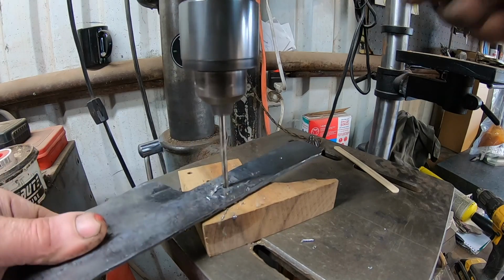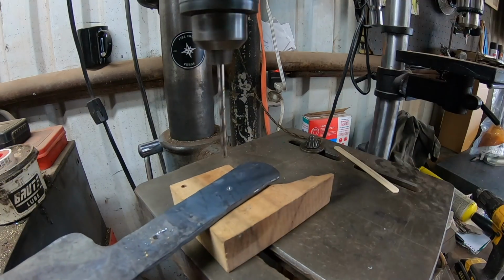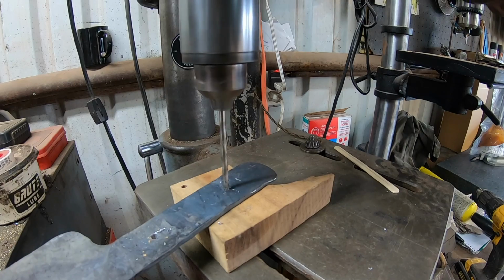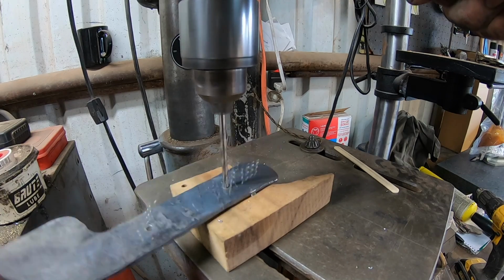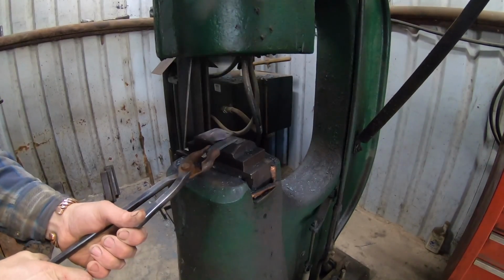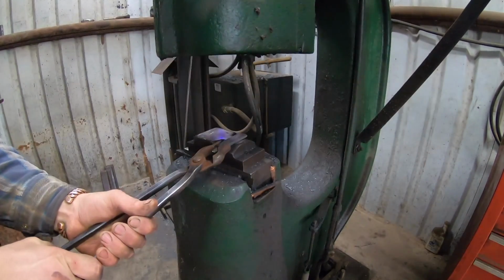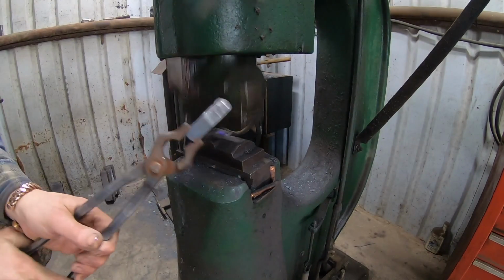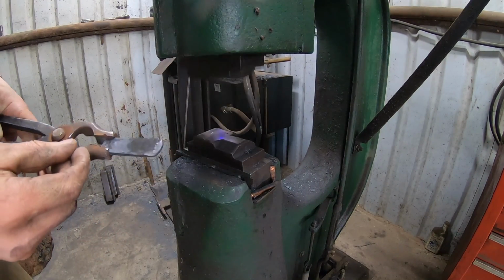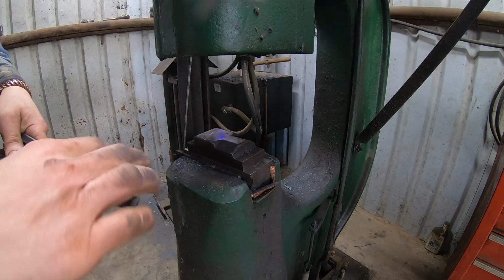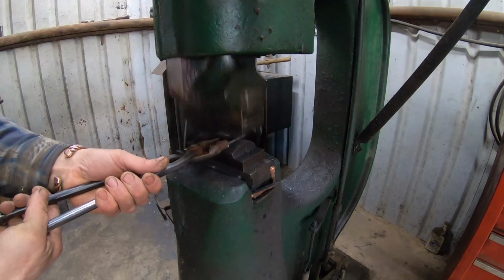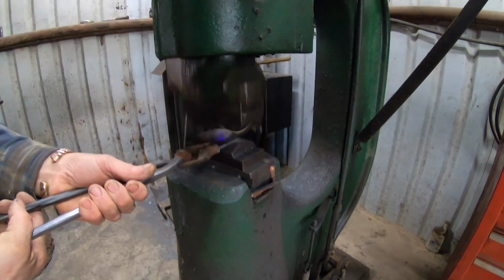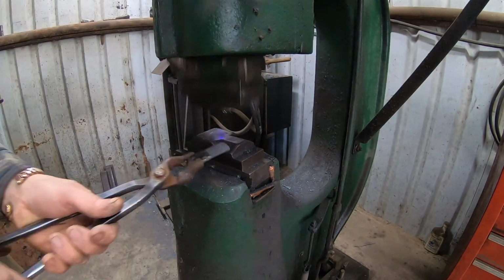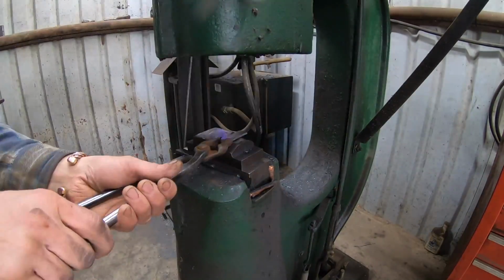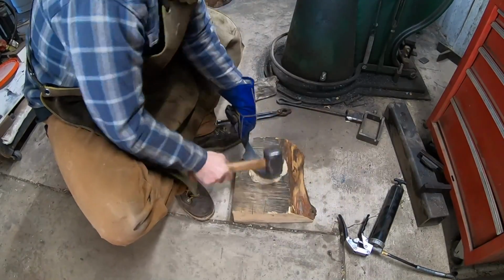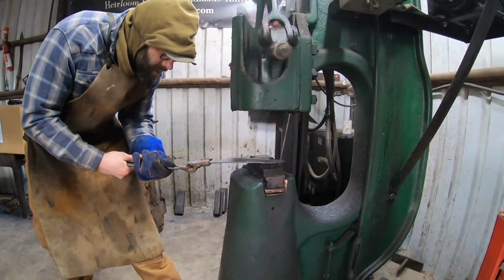This is something I was really interested in checking out, and that is drilling holes in the tang for the handle bolts. It went very well, and the steel was quite soft, and the drill bit didn't even squeak. It would not happen with steel like 52-100. That wouldn't work. My sample piece did get a crack from cold forging, but again, it is not cushioned by the mild steel cladding, and so the process is not exactly the same as with the actual blades. I'm hoping it's close enough, though, to give us a good idea of what the heat treat comes out as.